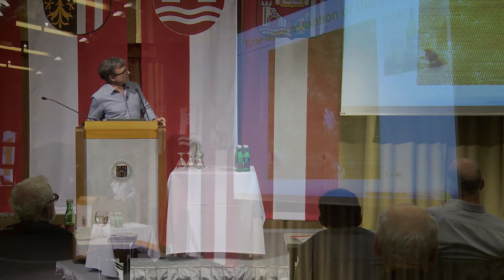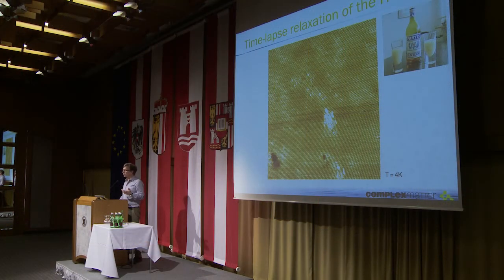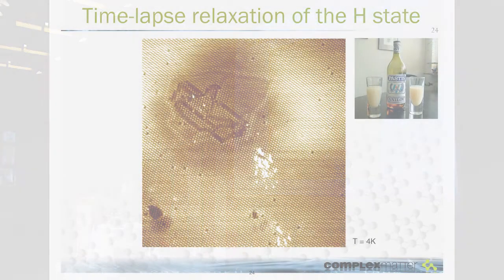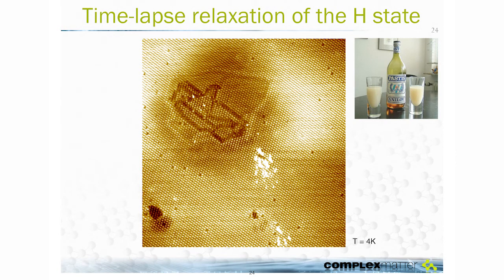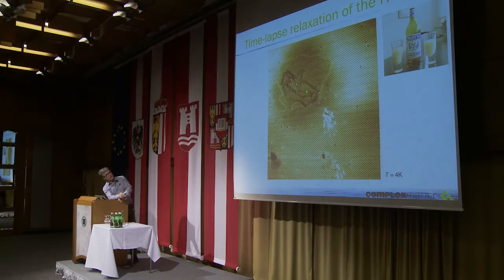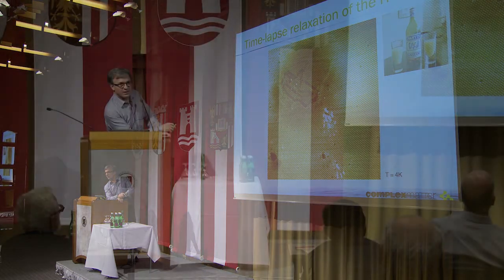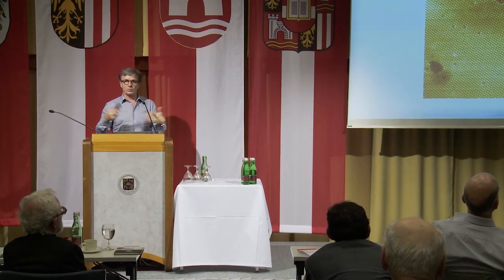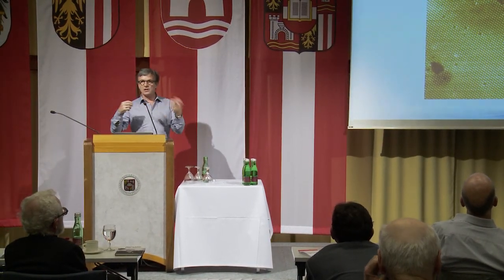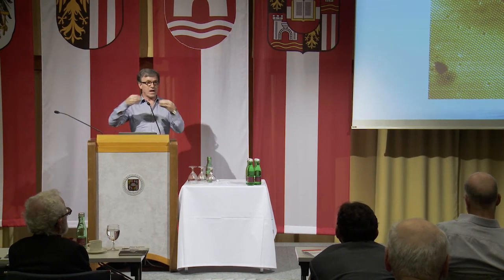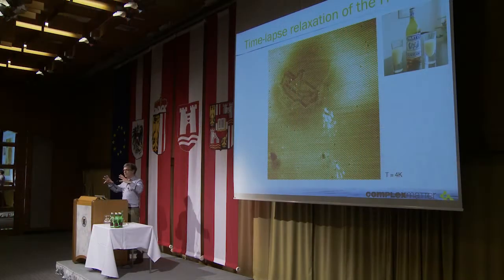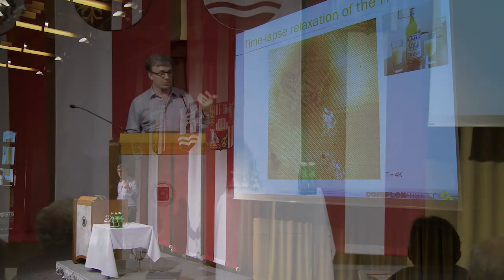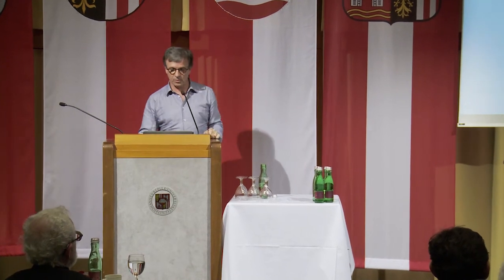Right. Here's a beautiful, the reverse process. If you spontaneously leave the material, it will actually relax. And if you notice these features here, it doesn't relax one polaron at a time. It relaxes one line at a time. And this is related to topological protection. In other words, there's no single particle excitation that can relax your polaronic crystal. You have to relax the whole line. That's a topological argument.